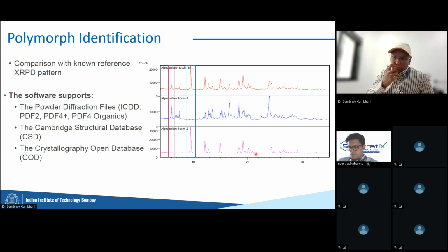And this is essentially what we do. That's what we call comparison to reference. These are pure material reference databases, right? We compare them to our actual sample, and we can also quantify the exact concentration of polymorph 1 and 2 in this actual batch. That quantification process is known as Rietveld refinement. So it's not that morph 1 is completely absent.